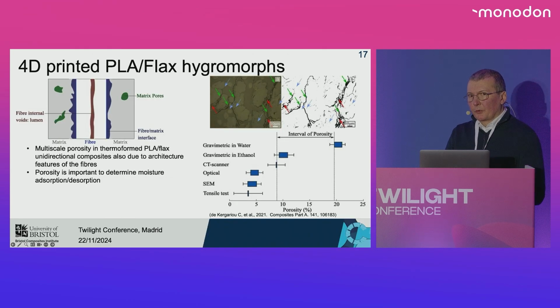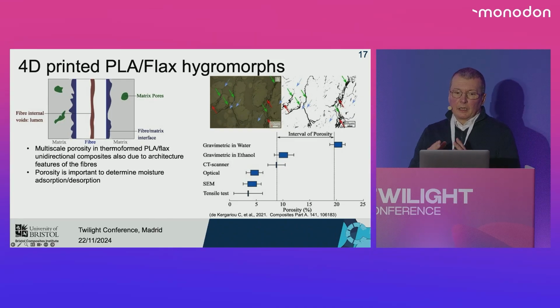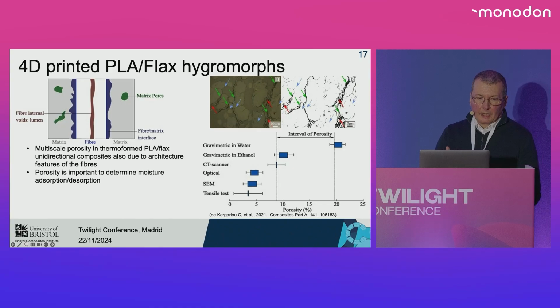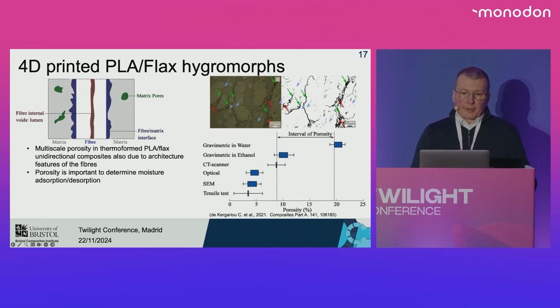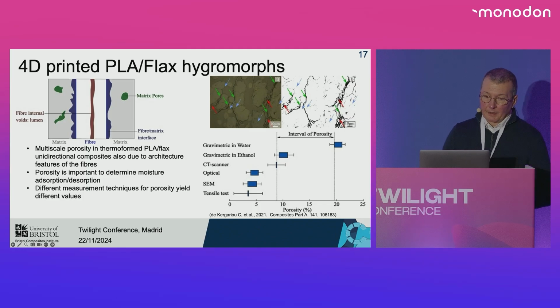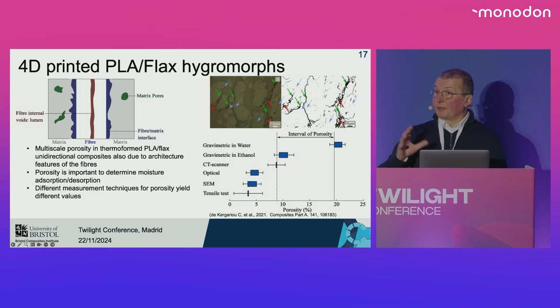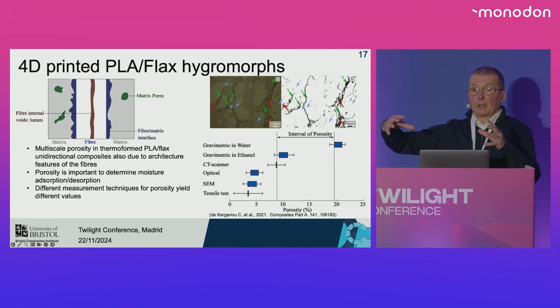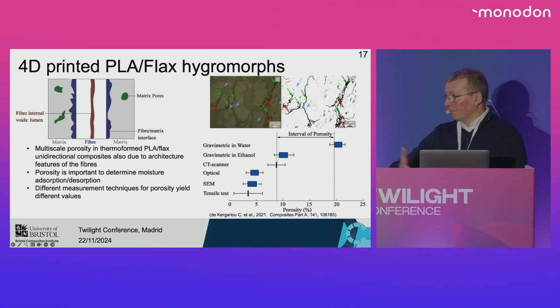Something that needs to be understood when you use natural fibers is the effect of the porosity of the fibers in the composites. Composites made using natural fibers have not only porosity in the matrix and at the fiber matrix interface, but also inside the fiber itself, because of the presence of the lumen. So we have a multi-scale porosity, and you need to consider the porosity in terms of efficiency of the actuation. And the porosity is also important to determine the characteristics of moisture desorption. So we had to develop a special type of measuring technique beyond the classical gravimetric technique in water that is used to assess the porosity of classical composites.